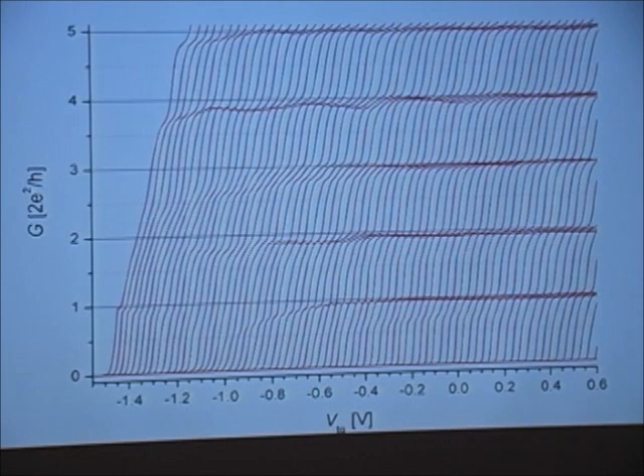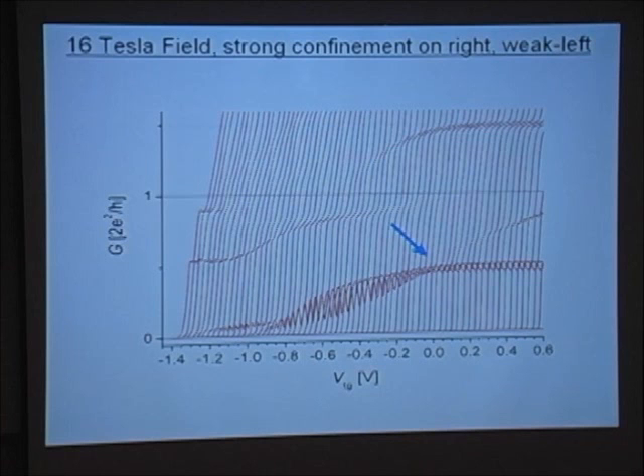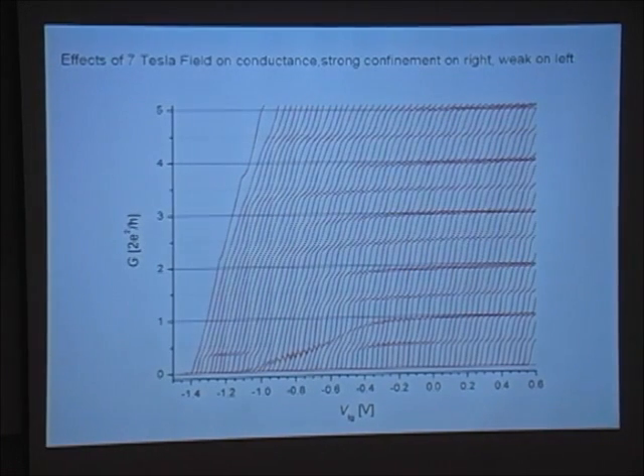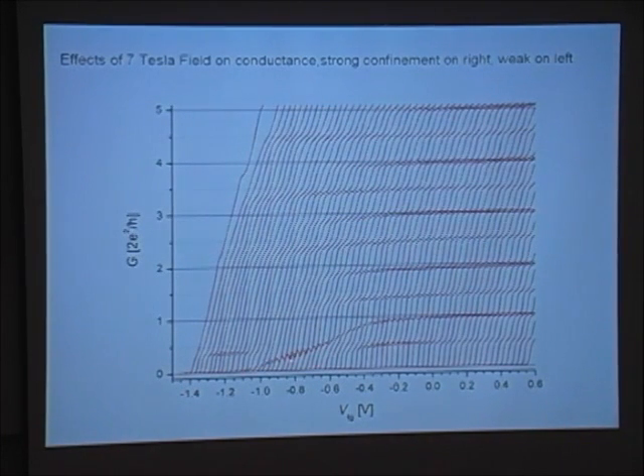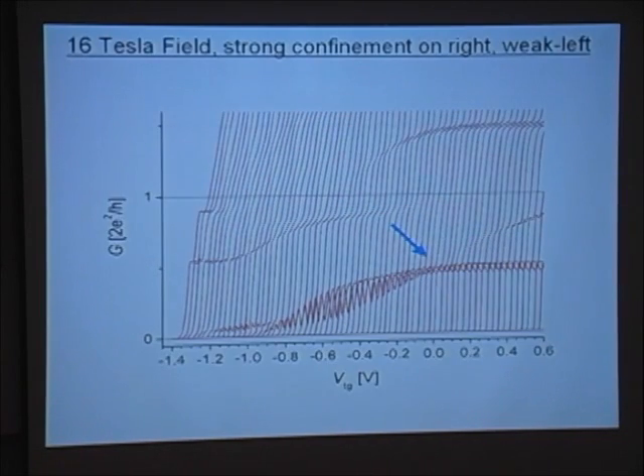Further, you can get quite spectacular examples of this sort of behavior. I just want to show what happens in a high magnetic field. This is a high magnetic field which actually completely changes the energetics by lifting the spin degeneracy. The only thing I want to draw your attention to is this oscillatory behavior here, which looks very much like an envelope, like a beating. This is at a lower field. You can see it there, actually. And it becomes bigger as we increase that magnetic field. There it is.